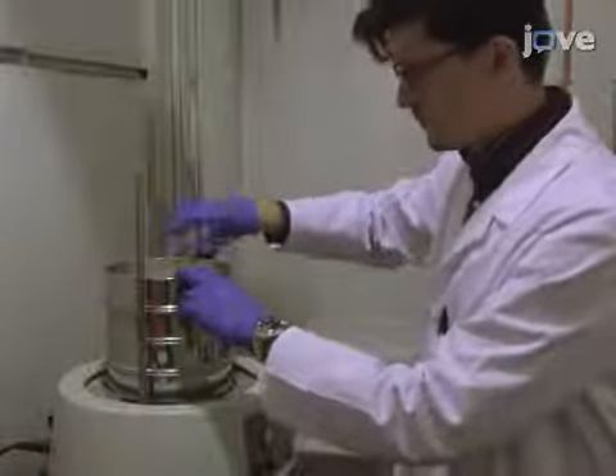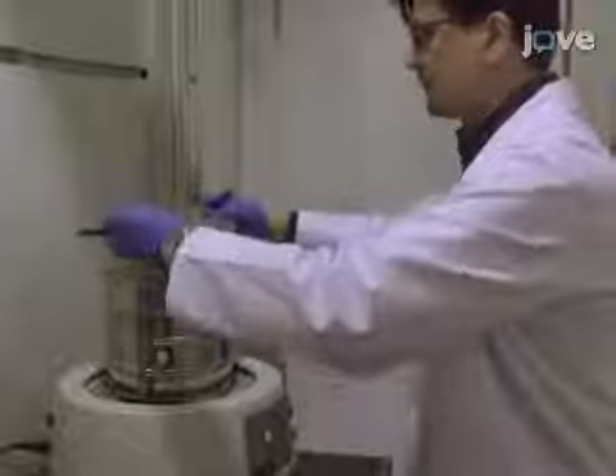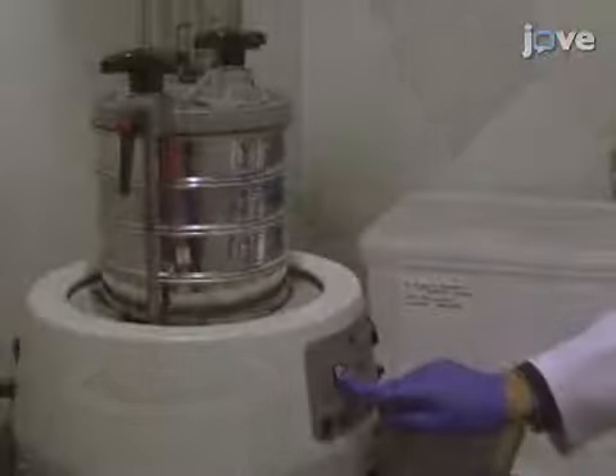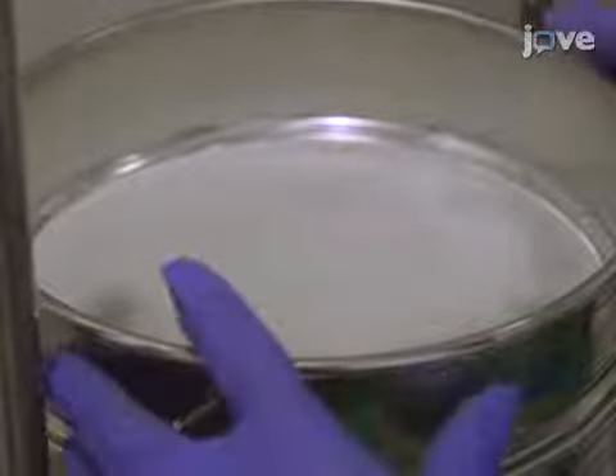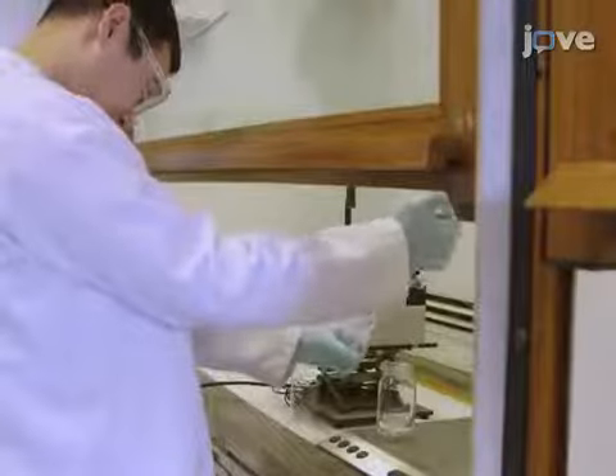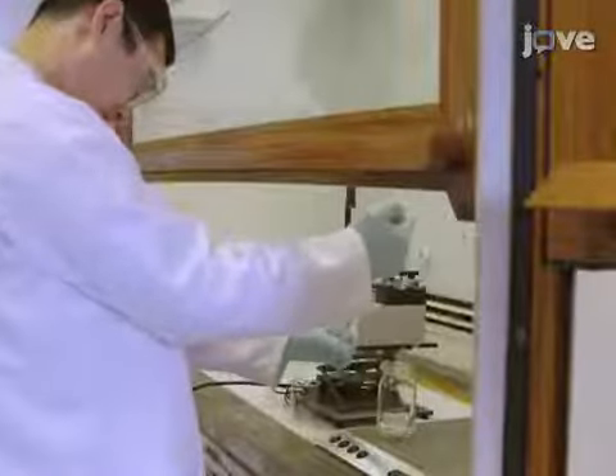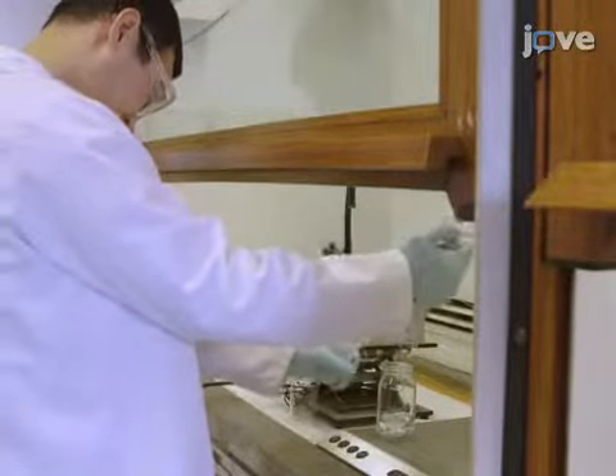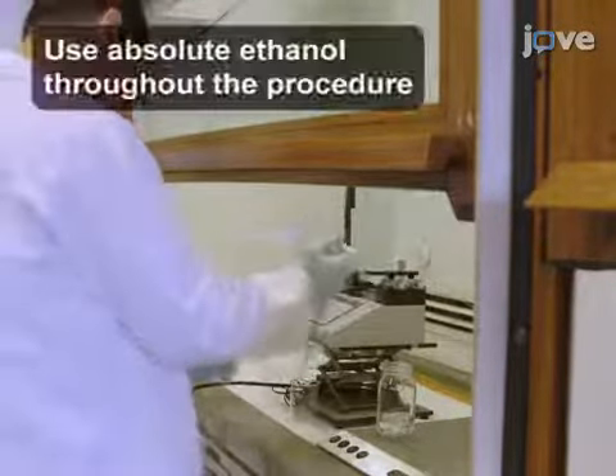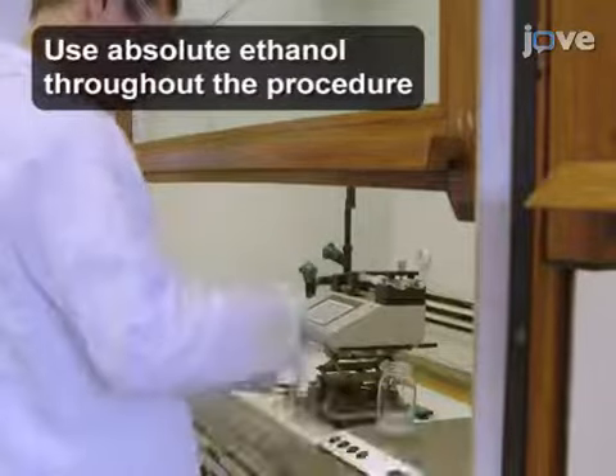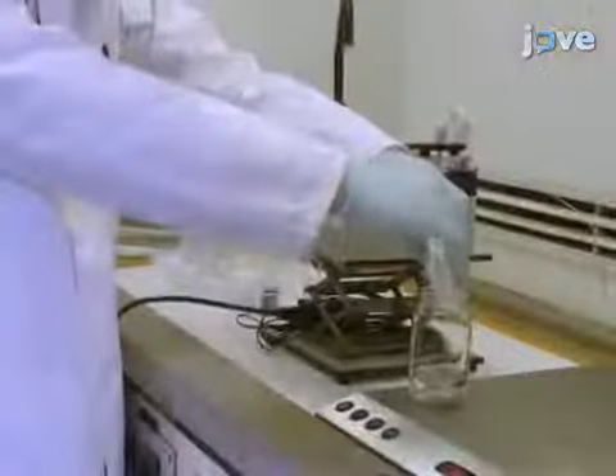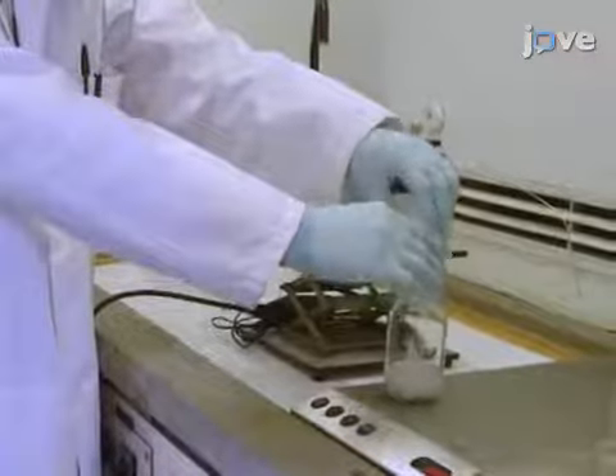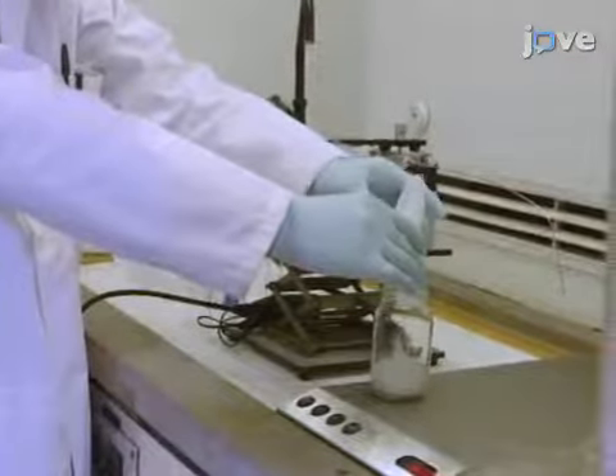To prepare the QT1 composite, first ball mill commercial quartz for 15 minutes. Sieve the milled quartz powder to obtain quartz particles with sizes ranging from 20 to 100 microns. Next, mix 2.6 milliliters of 97% titanium butoxide with 29.6 milliliters of absolute ethanol to produce a titanium precursor solution. Suspend 3 grams of the milled sieved quartz powder in 30 grams of the titanium precursor solution. Add to the suspension